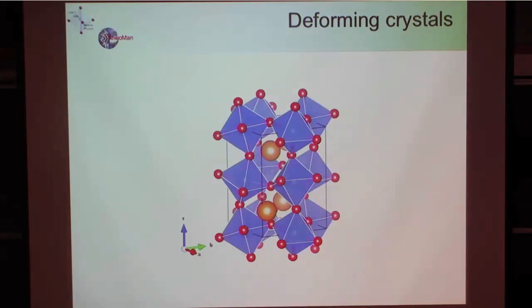So basically the difficulty and the problem that we have is to reconcile crystallography, which is ordering, and flow. You know, flowing water is not a problem. It's a disordered medium, so you go from one disordered configuration to another disordered configuration. There is no fundamental problem with that. But here we have a crystal structure, it's ordered, and we know that after plastic deformation, if we X-ray the material, it's still crystalline, so we need to preserve crystal ordering during plastic deformation. How do we do that?